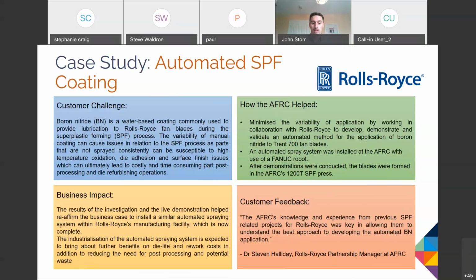So we worked in collaboration with Rolls-Royce to develop and demonstrate an automated method for application of boron nitride to Trent 700 fan blades. We installed an automated spray system at the AFRC with use of robotics, and we demonstrated trials through spray coating fan blades, and these were then formed in our 1200-ton press, as well as analysis being done on coating thickness and the consistency that we were able to achieve for that.